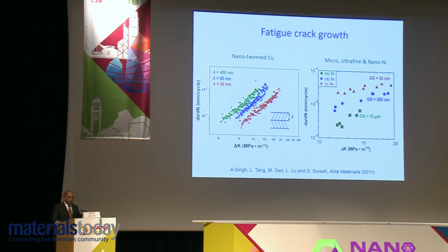This is work done in collaboration with Lei Lu and her student in Shenyang, and my PhD student, Aparna Singh at MIT. And what you see here is that when you introduce nano-twins, there is an opportunity not only to preserve ductility while increasing strength, there may be an opportunity also to provide some improvement in fatigue crack growth resistance. The problem remains that you cannot make these specimens in large quantities with enough thickness for a structural component where fatigue becomes an important criterion.